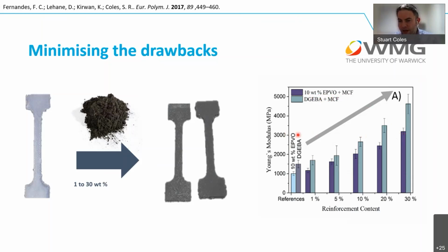In the DGEBA, we've now reached a level where we're at about 3 gigapascals of Young's modulus, which is fairly decent for an epoxy resin. We're not out of the realms of what could be considered a fairly decent material, but it's only 10 weight percent. It's still low in terms of its bio-based content.